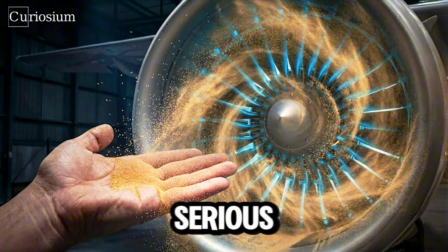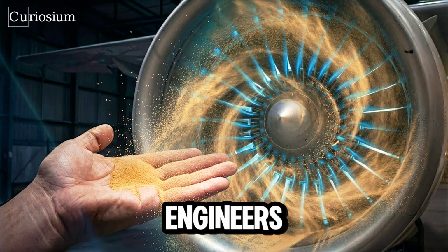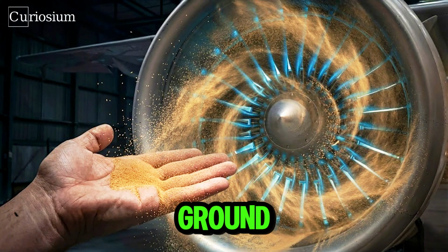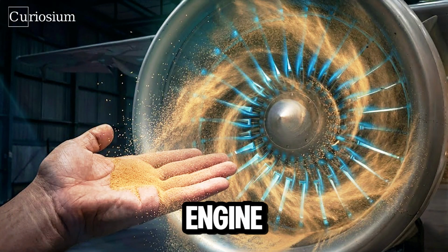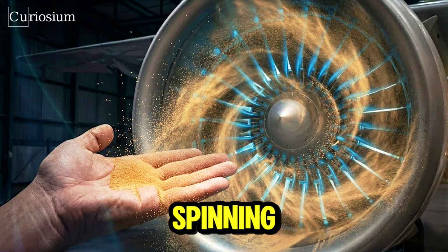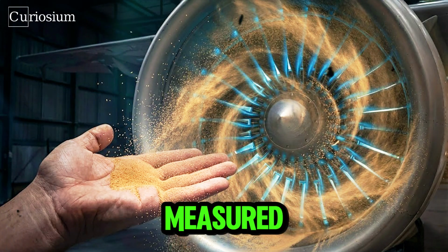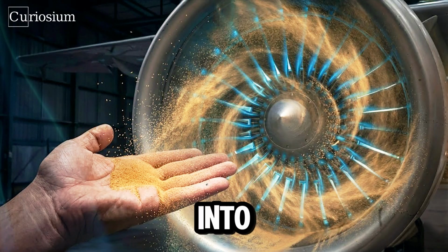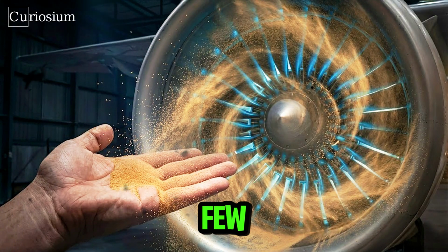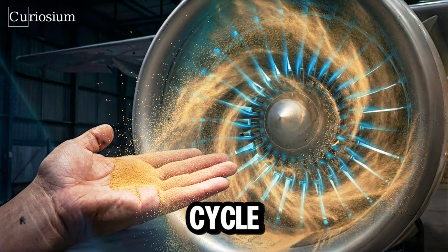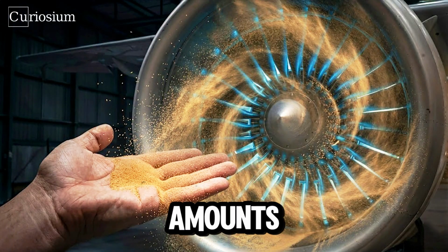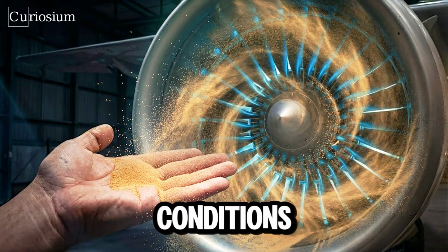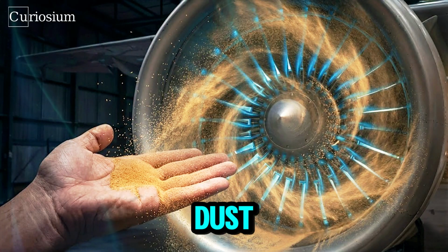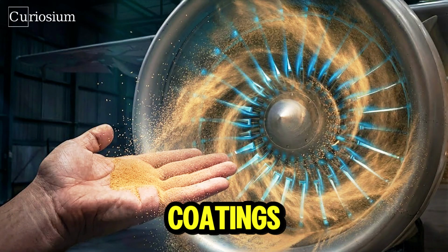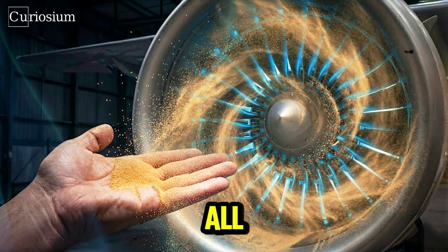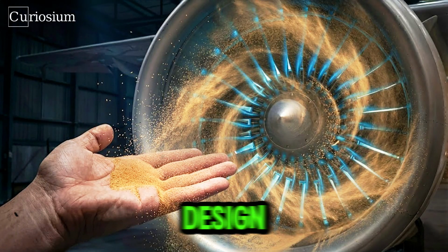To find out how serious this problem is, engineers run full-scale tests on the ground. Picture a jet engine mounted in a test cell, spinning up to full power. Measured amounts of dust are injected into the inlet, sometimes only a few spoonfuls over an entire test cycle. Even those small amounts can cause noticeable damage if the conditions are right. The dust attacks the thermal barrier coatings and slowly undermines all the careful cooling and alloy design.